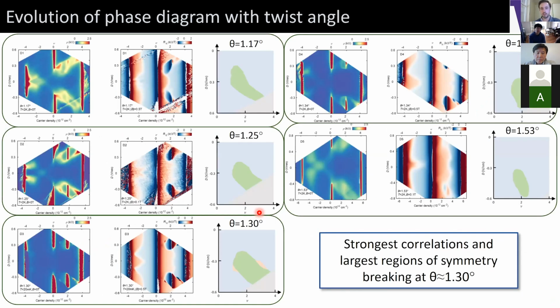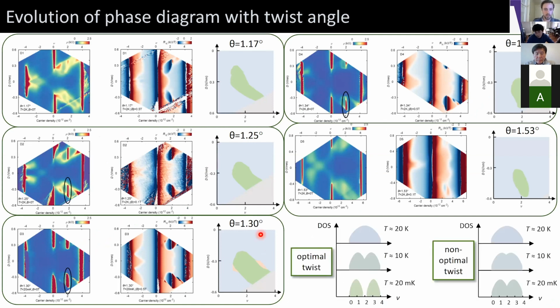the ability to tune the phase diagram with twist angle. So this is kind of a data dump, but what I want you to look at are these phase diagrams that we can construct from the Hall coefficient. As we tune the twist angle, the region of symmetry breaking grows until it's roughly maximal at 1.3 degrees. You can also see that there are only correlated insulating states around 1.3 degrees. For lower or larger twist angles, we don't see a correlated insulating state, but we do still see this symmetry broken region. So that suggests that even when we're at a non-optimal twist angle, and even when the bands don't fully gap, you can still be sensitive to the fact that you have some sort of spontaneous symmetry breaking in the system as you cool it down.